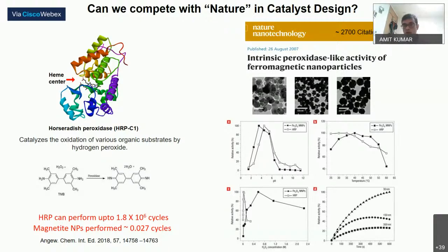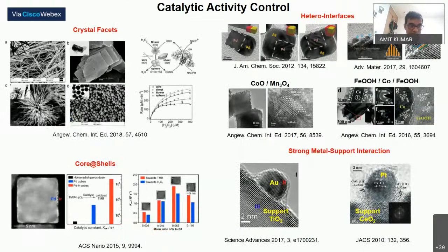But the development of nanoscience gives us the opportunity to tune the activity of catalysts. A lot of research has taken place in the last decade, with many remedies to modify the catalytic activities of nanocrystals. One of them is controlling the crystal facets by changing their shapes and sizes, and also making binary and ternary systems, for example, core-shells, which have been shown to have very high activity in combination. Metallic hetero-interfaces can also increase the catalytic activity, and strong metal-support interaction is another method. These are common approaches by which scientists have enhanced the catalytic activity of catalysts